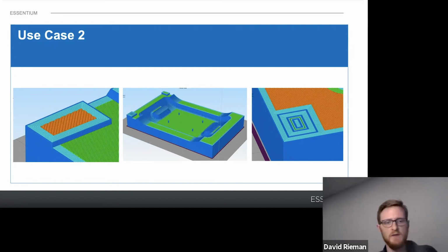What the crash pads do is that as the molds come together, they keep some of the pressure more evenly distributed, so that it's not all entirely pressing on that pinch point and possibly damaging that thin piece of material. You want to help distribute the load. Even though the pressure the parison puts on the part when it's being blown is fairly low, the molds have to be pressed together at a pretty high pressure, so they need a lot of strength there. And as the parison is blown out, the molds are going to want to release and pull apart from each other. That's why blow molders will oftentimes add even more pressure during the blowing process to make sure those molds stay together.